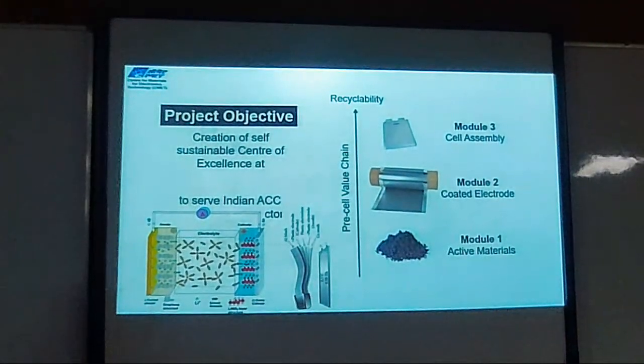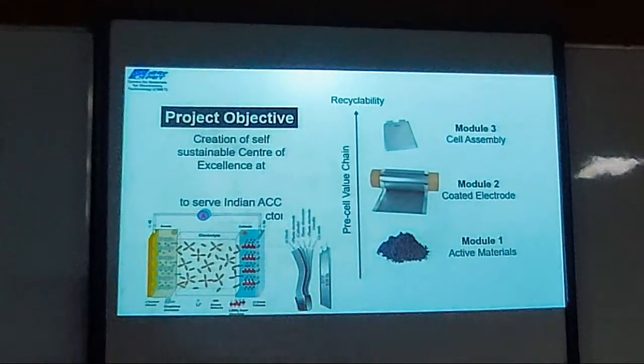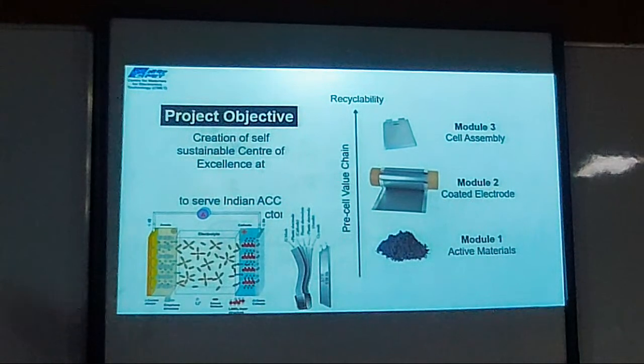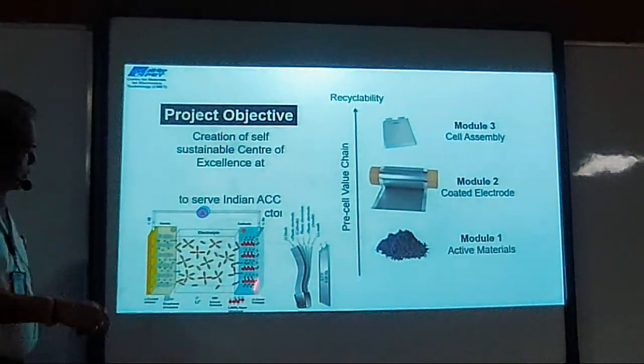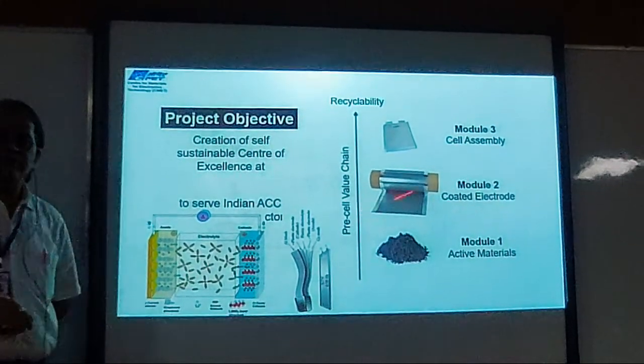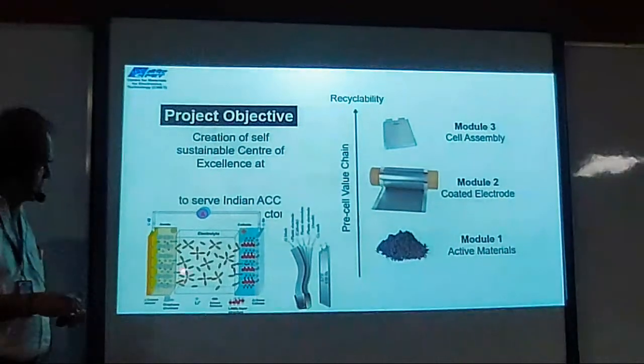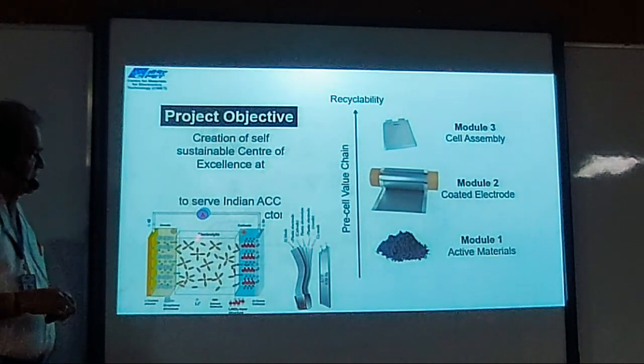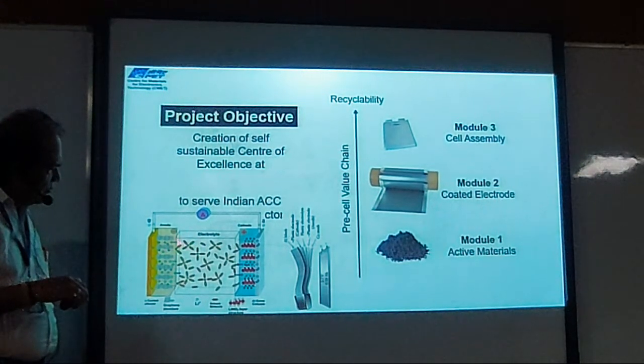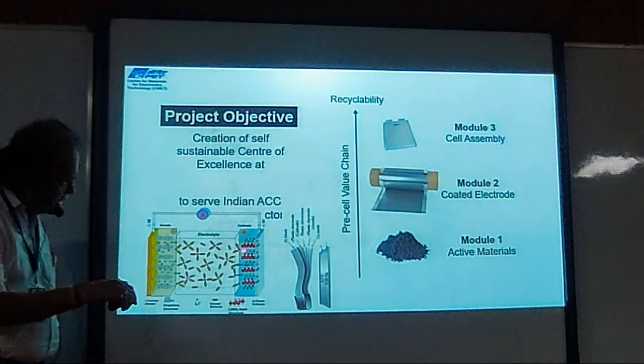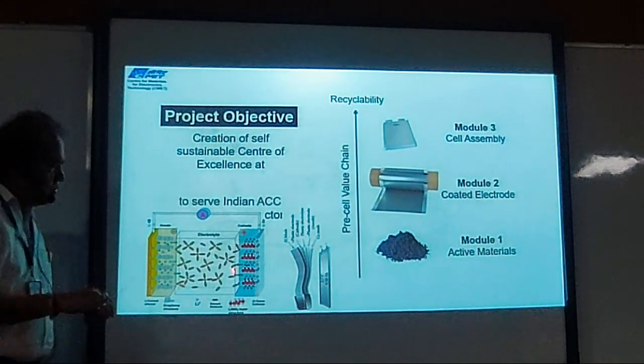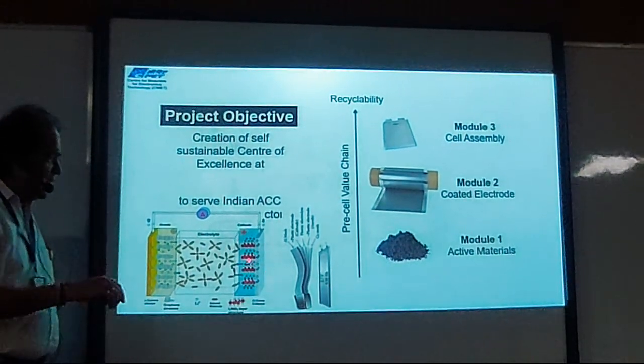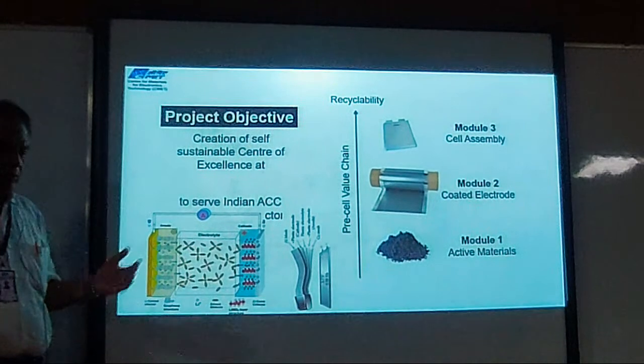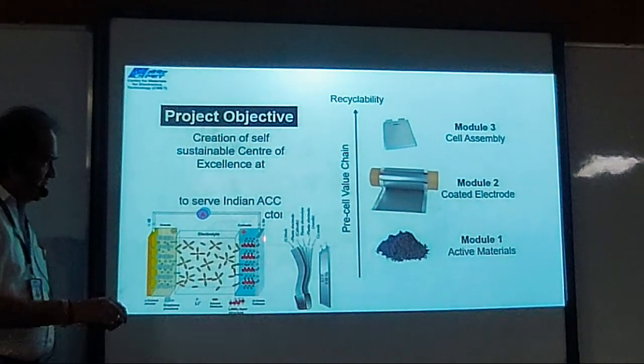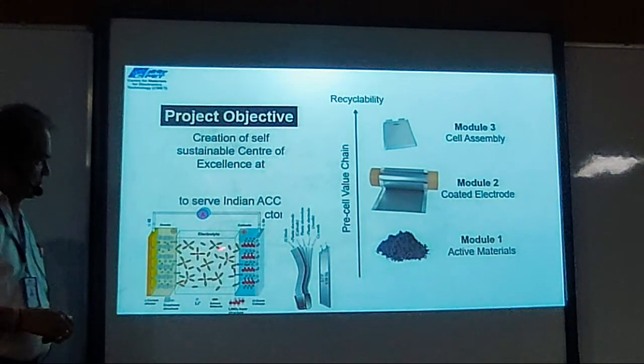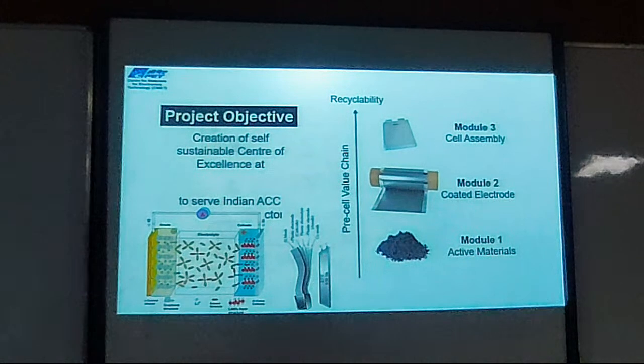Today my battery has 1,000 cycles, so that it can run 1.5 years, because one day we can charge with one cycle, right? So how to improve materials? Materials should have a layer structure. Both materials, anode and cathode, should have a layer structure. Why is the layer structure required? When ions get transferred from anode to cathode, they should sit here in the layers. More accommodation of ions in the layer structure gives the maximum amount of storage, right? So we are developing cathode and anode of layer structure, so that we get the maximum amount of energy storage.